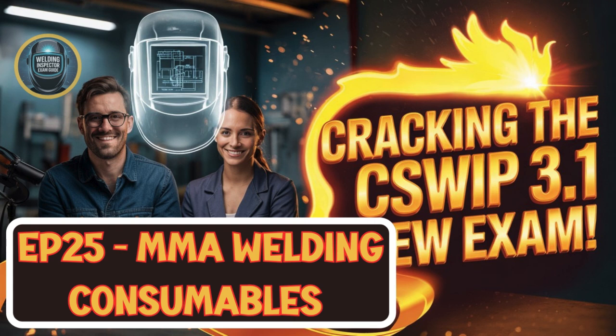Now, regarding hydrogen, you can dry them gently to lower the content a bit, maybe down to 25 or 30 milliliters per 100 grams. But like cellulosics, you absolutely cannot bake them at high temperatures. It destroys the coating. So it's still some hydrogen, but less than cellulosic. Yes, significantly less. But their main limitation is that you can't get them down to very low hydrogen levels. That means they're generally not suitable for high-strength steels or really thick joints where that hydrogen cracking risk becomes a major concern again. And similar to cellulosics, they don't offer particularly good toughness at very low temperatures. Great all-rounders, but not for the most demanding high-integrity jobs.